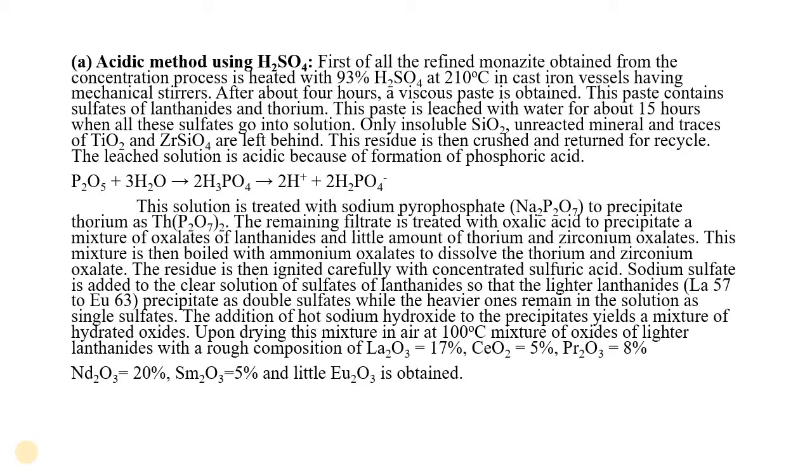In this process, after 4 hours, a viscous paste is obtained. Sometimes we call this viscous paste mud, M-U-D, mud. This paste contains sulfates of lanthanide and thorium. This paste is leached with water, shaken with water, mixed with water for about 15 hours, when all these sulfates go into solution.